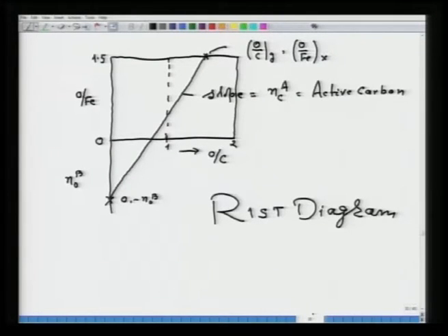Remember, we started with the pure liquid iron, pure Fe2O3. Now, with this addition we have come closer to what is happening in actual blast furnace iron making. We brought SiO2 of the gangue into the picture, we brought MnO2 of the gangue part of the ore into the picture, we made liquid iron, and we added silicon, manganese and carbon. So, heat demand can always be updated according to the actual situation. Now, after understanding this, we can modify the material balance equation to incorporate the heat balance equation also.